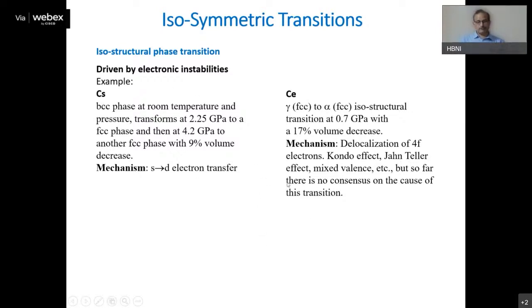Mainly the driving force for these phase transitions is electronic instability. Like in case of cesium, as you increase pressure, the energy of the s band increases, and so there is electron transfer to the d band. And this d band basically localizes these electrons, and this gives rise to a volume collapse in the structure. In this case, you can see there is a volume collapse from FCC to FCC of about 9%. So this is a kind of isostructural, isosymmetric phase transition.